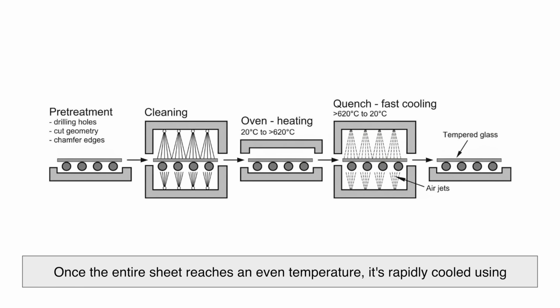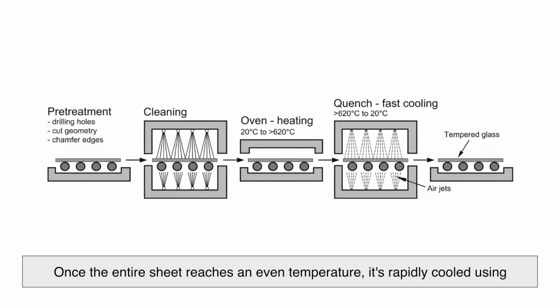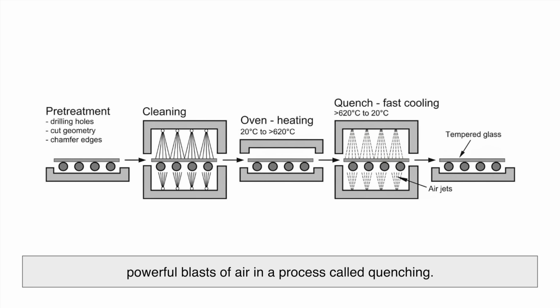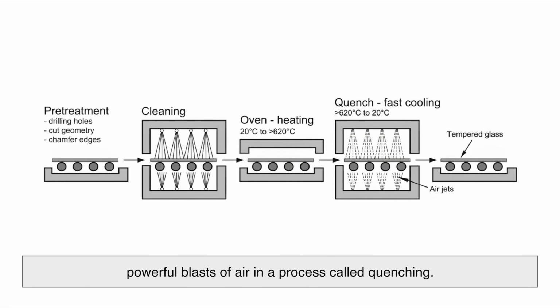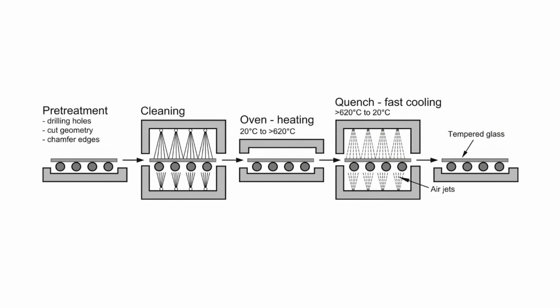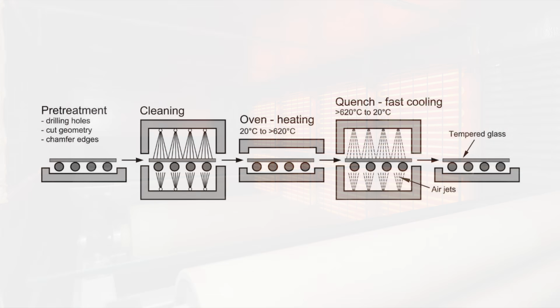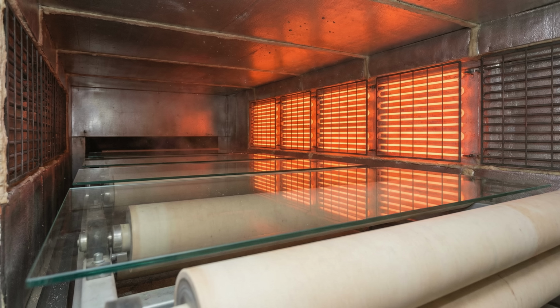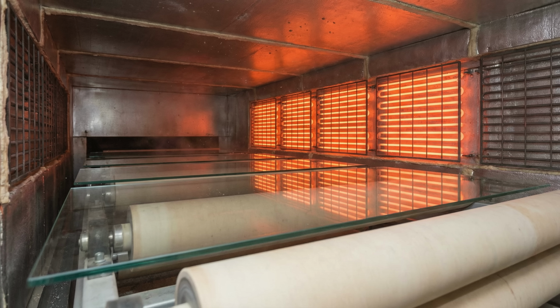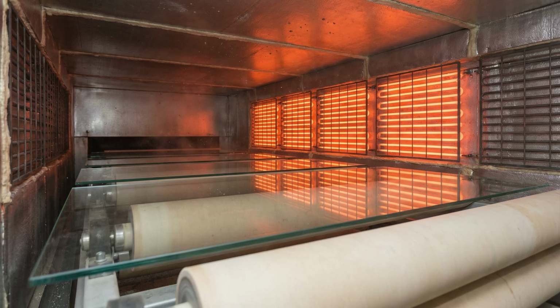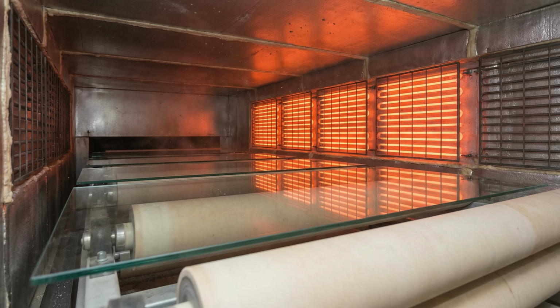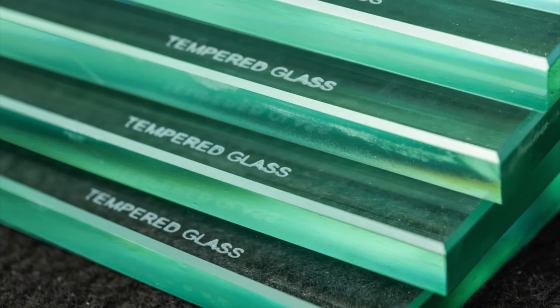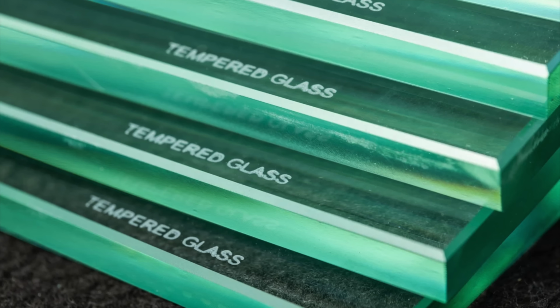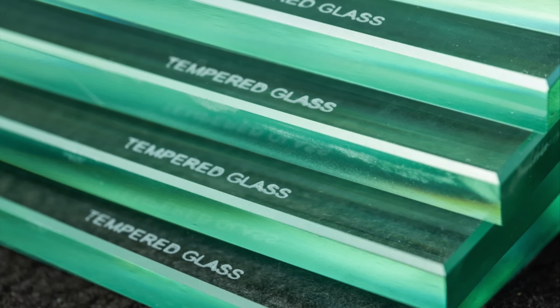Once the entire sheet reaches an even temperature, it's rapidly cooled using powerful blasts of air in a process called quenching. This sudden cooling hardens the outer surfaces almost immediately while the inner portion cools more slowly. As the center eventually contracts, it pulls against the already hardened outer layers, leaving the surface under compression and the interior under tension. These internal stresses are what give tempered glass its remarkable strength.